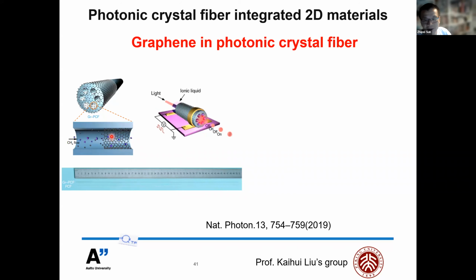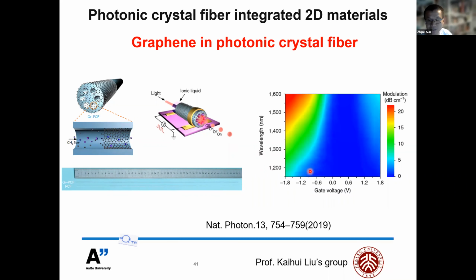For example, here, Professor Kai-Hui Liu's group in China has demonstrated the ability to deposit graphene inside of a photonic crystal fiber. Then we worked together to use these hybrid fibers for optical modulators with a very large modulation depth of up to 20 dB per centimeter. You can see the light matter interaction is much more enhanced if you compare it to the absorption of monolayer graphene, which is only 2.3%.